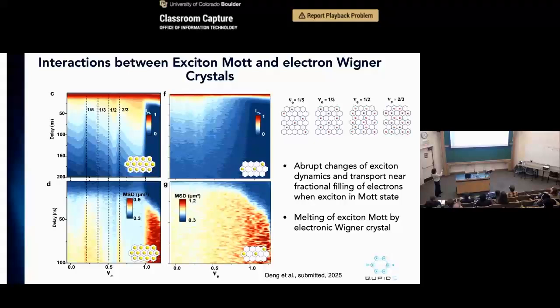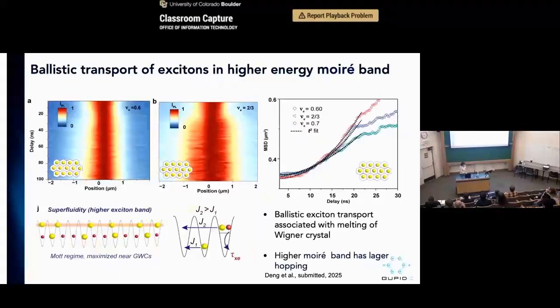And the most obvious one is around 2/3. So I'm just going to explain that one in particular. What you see at around 2/3 is that the lifetime becomes shorter. Blue is just low density, so it just means that it decays faster. And the spread of the exciton, the MSD, becomes faster because yellow just means higher MSD. So when these excitons are nearly correlated electron states, and the exciton is also correlated, they have these very abrupt changes.